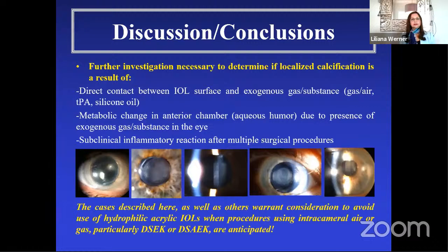At the beginning, we thought that this complication was related to the direct contact between the IOL surface and substances such as air, gas, or silicone oil. However, this complication was also observed without the use of vitreous tamponade. Therefore, we believe that there may be a metabolic change in the aqueous humor due to the presence of these substances in the eye. And there is also likely an inflammatory reaction that may be subclinical in these eyes undergoing multiple procedures.